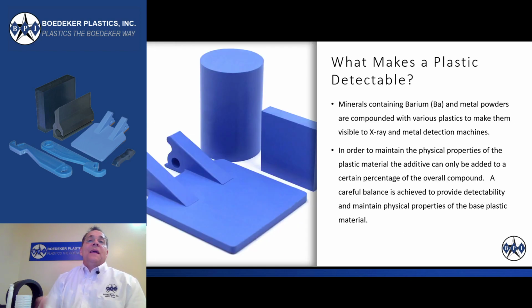Now, how are these materials made to be metal detectable? Well, how do you make a product detectable with metal detectors? You have to put metal in it. So basically metal powders are put into the polymer. For X-ray detectability, you have to put powder in as well, but in this case it's a barium powder. The barium filler is what enables the material to be seen on the X-ray detection systems. So these powders are blended into the raw material resin, compounded in prior to them being extruded or injection molded.